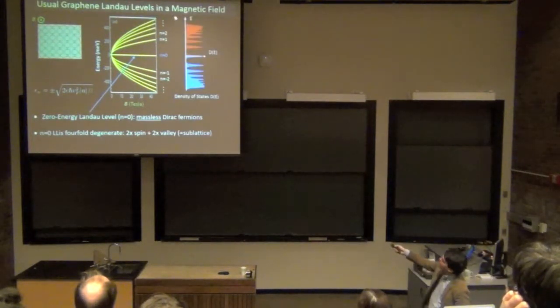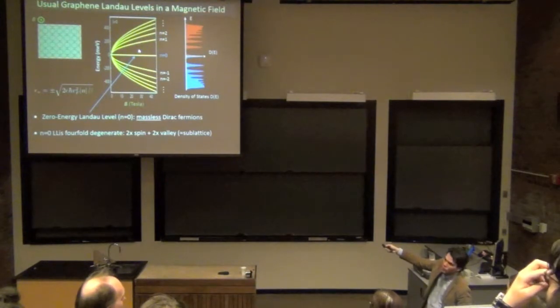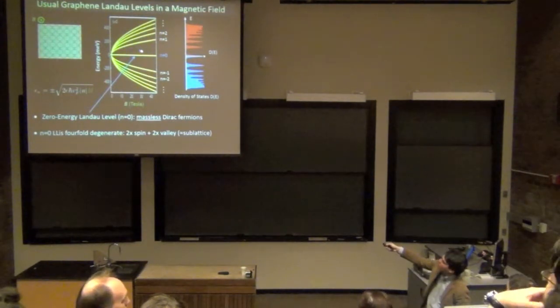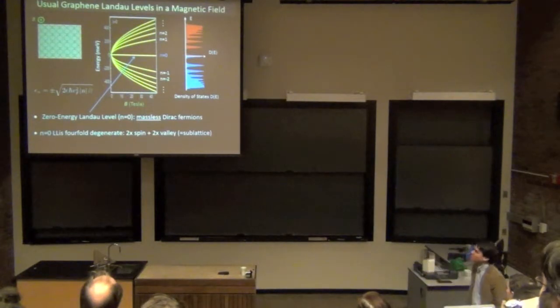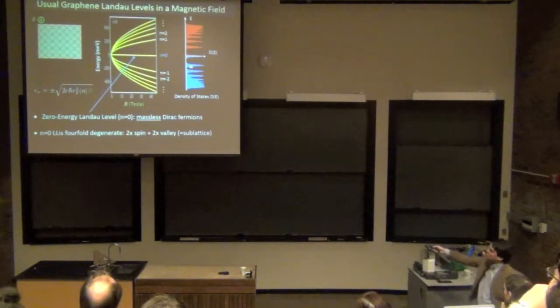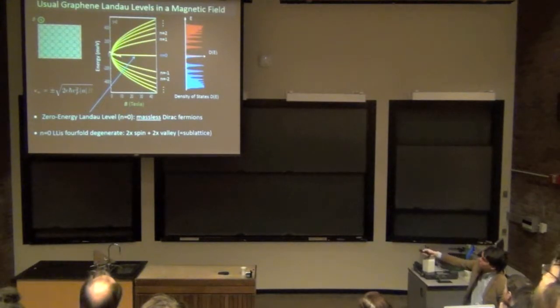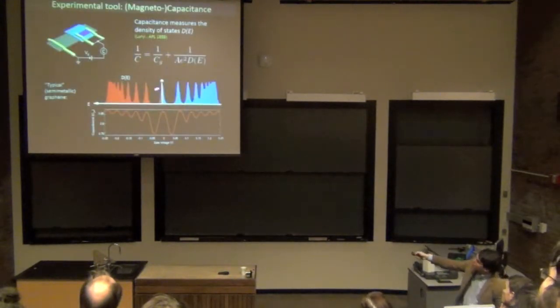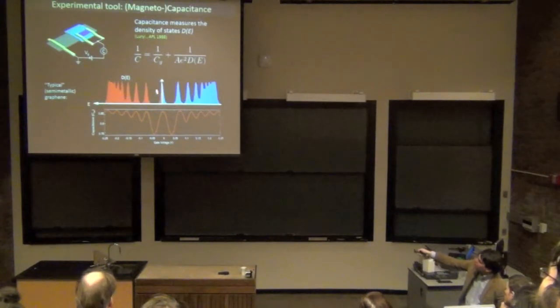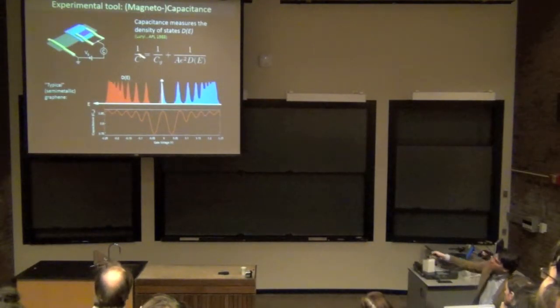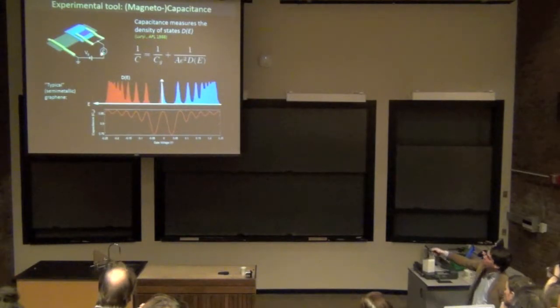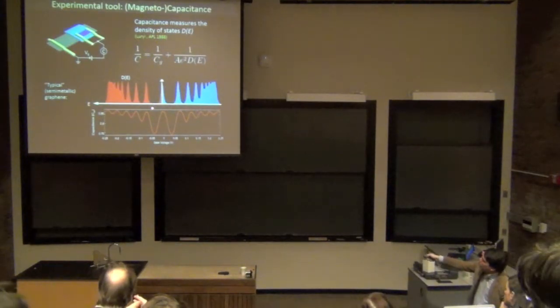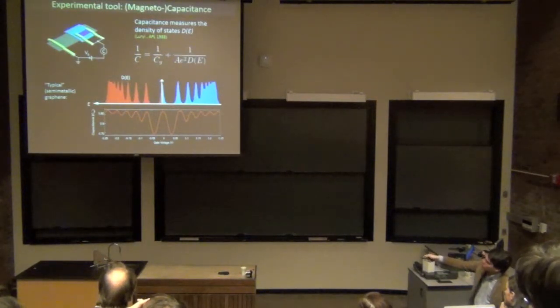Okay, so if you look at the density of states here, if you take a cut at fixed magnetic field, the density of electronic states is very high when you're in one of these electronic bands, and it's very low when you're in one of these gaps between the Landau levels. Again, the n equals zero Landau level is characteristic of massless Dirac fermions. And we can measure in a typical graphene sample this density of states based on a capacitance measurement that we can also do. So you can see a peak at zero energy here, which is characteristic of this semi-metallic graphene, of typical graphene.